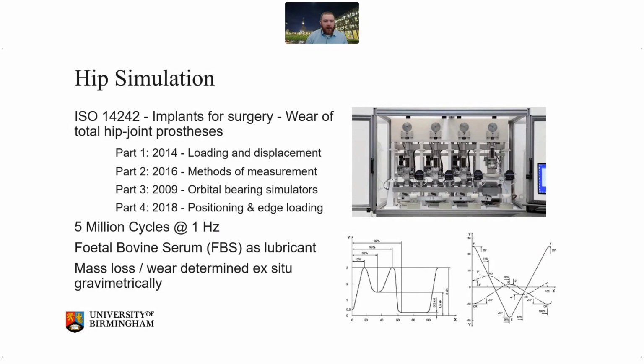Fetal bovine serum is used as a lubricant, and that's often diluted with deionized water. It doesn't have a lot of the constituents, like lipids and hyaluronic acid, that are present in synovial fluid. And mass loss is essentially determined gravimetrically ex situ. So the components are taken off every week, they're cleaned and they're weighed in order to determine a mass loss, and then that's your wear rate. That's your benchmark polymer wear rate to try and assess a change in device design or device material, to give an indication of whether or not that is going to be more or less likely to be successful compared to a device that's already on the market with clinical history and its simulator